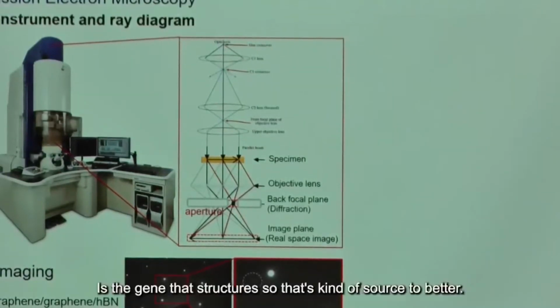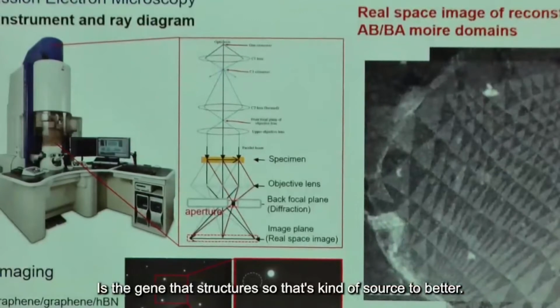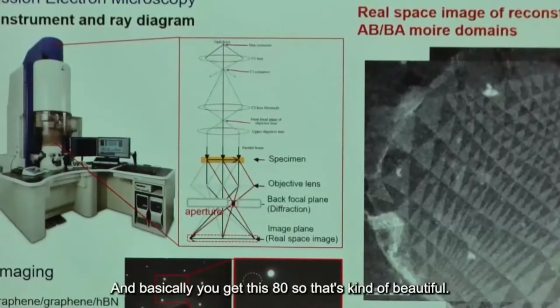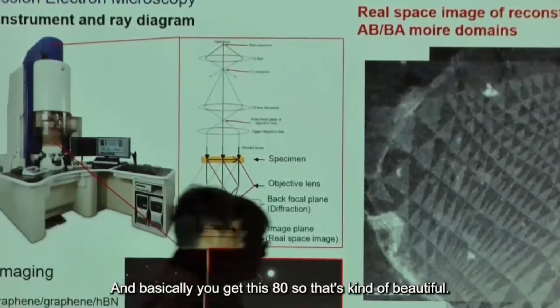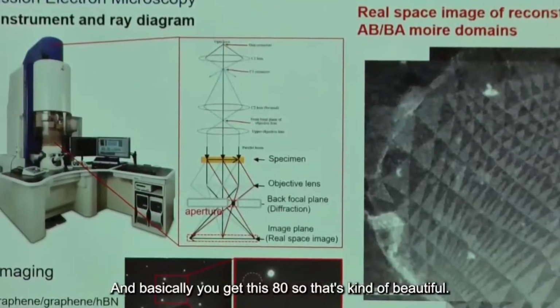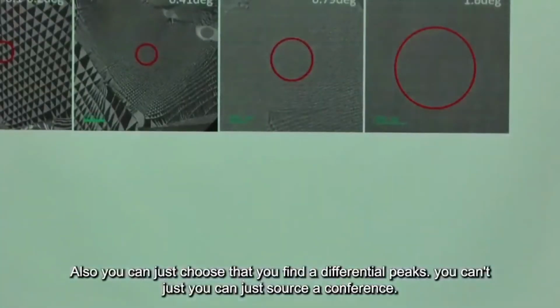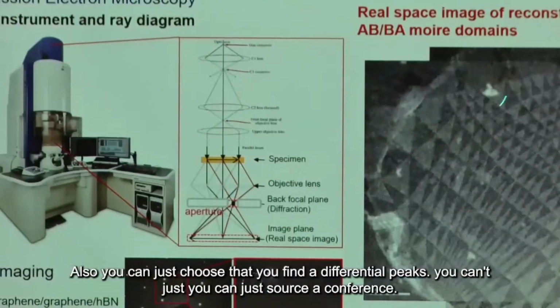With a small tilt of the sample, you can distinguish the AB versus BA stacking in that structure. So that's the structure matter. And basically in the images, you get this AB versus BA contrast by using this dark field imaging technique. So that's a beautiful technique. Also, you can choose different diffraction peaks, and also contrast this boundary more, which I'm going to show you later.